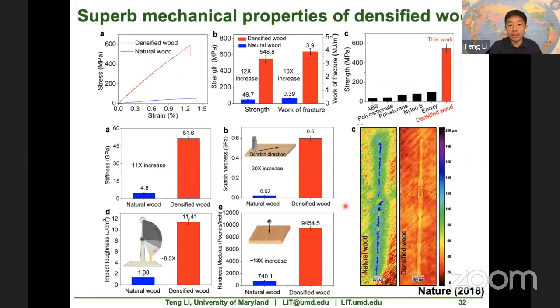So here I show the mechanical properties of densified wood. This is a stress strain curve. This is natural wood and this is the densified wood. And there is a 12 times increase of the tensile strength. The absolute strength when we were publishing the data was around 550 megapascal. That's already stronger than some lower grade steel. We know that steel has a very large range of strength depending on the composition. And the work of fracture increased 10 times. In terms of the stiffness, there was an 11 times increase.